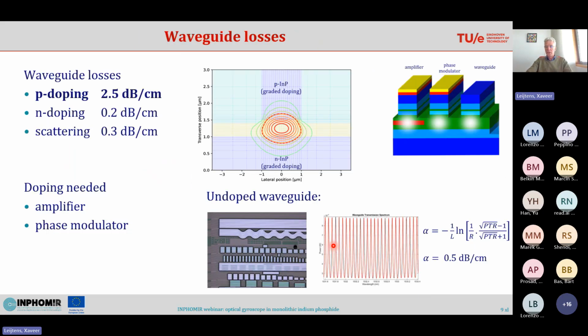Well, if we look in a bit more detail at the passive waveguide here, this is a cross-section with a mode solver. You can see that this mode overlaps a little bit with the p-doping on top of it. And that's the main problem that we have for the loss, because if you look at the breakdown of the losses, you see that the scattering from the roughness of the sidewall of the waveguide is 0.3 dB per centimeter. The N-doping doesn't influence the light so much, it is 0.2 dB per centimeter, but the P-doping is 2.5 dB per centimeter. So indeed, if you remove the doping and you measure passive waveguides, you get a loss which is 0.5 dB per centimeter or less.